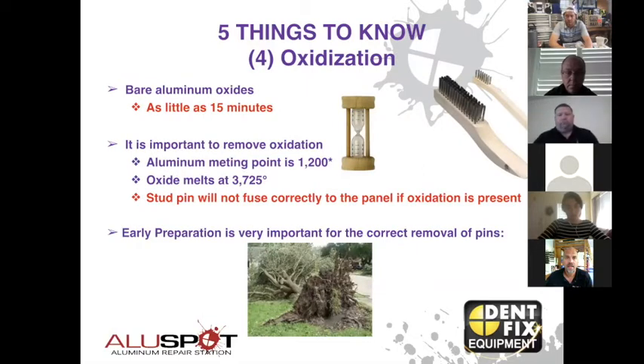Again, the aluminum will oxidize in as little as 15 minutes. We provide these shoehorn and toothbrush style stainless steel brushes. Oxidation, you're going to use those stainless steel wire brushes, and you're going to vigorously sand away your oxidation after the paint's been removed.